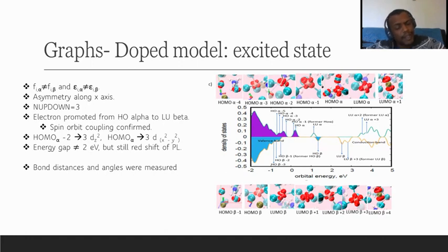to confirm the orbitals contributed by the manganese ion electrons in the d orbitals, and we can see here that the HOMO alpha minus 2 is having the Z squared, I believe, but I wasn't very sure. So after that, what we did is measure the bonds and the angles of the chlorine, manganese, chlorine. And next slide, please.